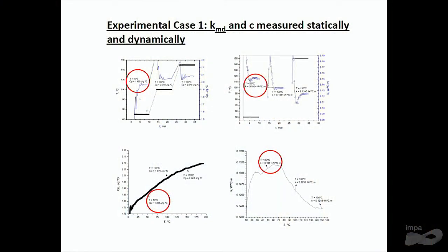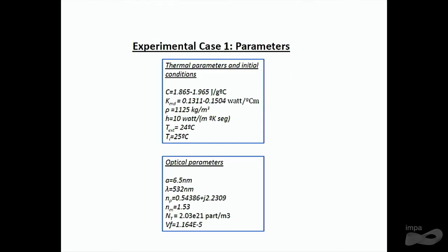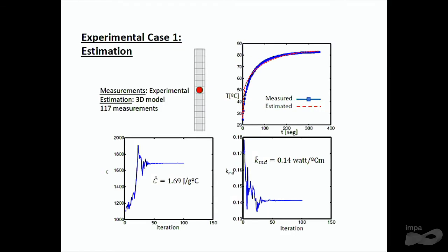We would like to see what values, when you put them into the model, allow us to adjust the temperature values using the heat transfer equation, and how the parameters converge to some values. And this is what we obtained. For the first case, the blue one is the experimental, the red is the theoretical, the estimated. And these are the parameters we obtained in this case, heat capacity and heat transfer coefficient.